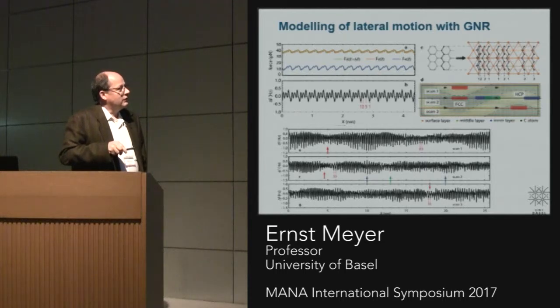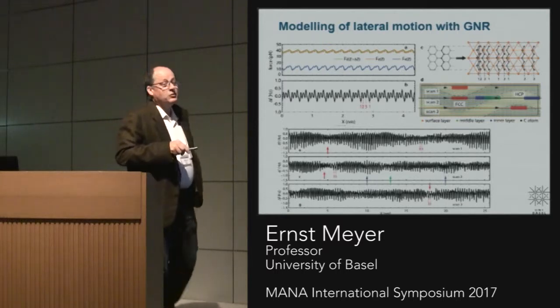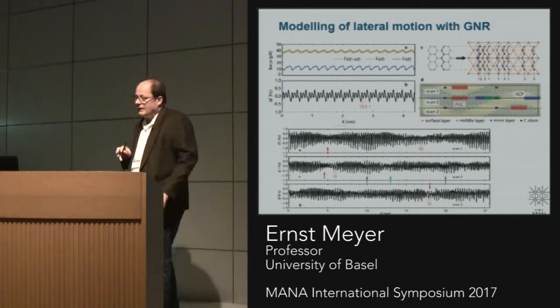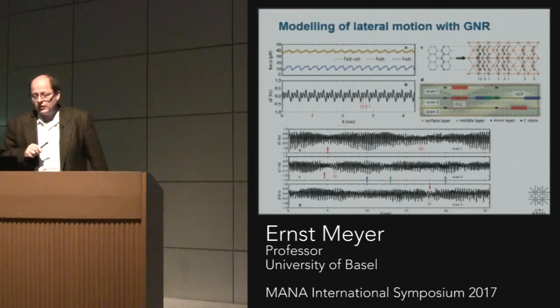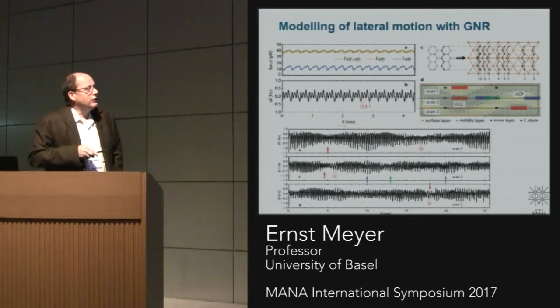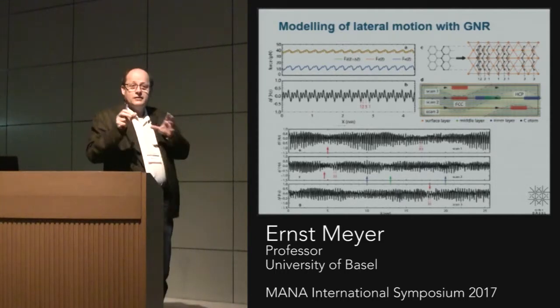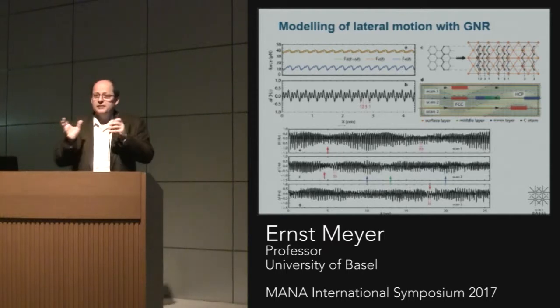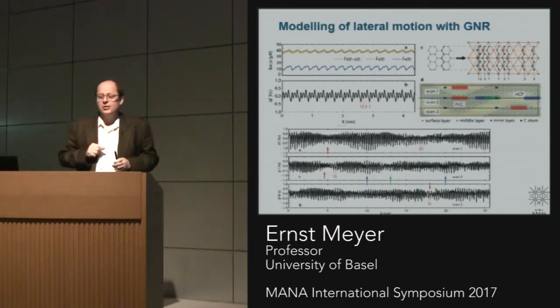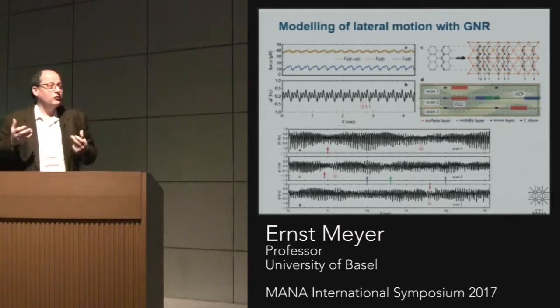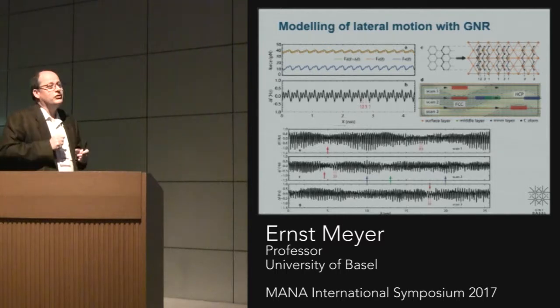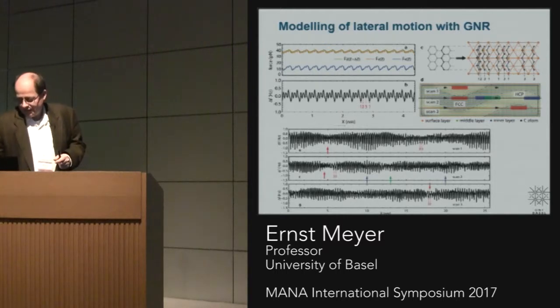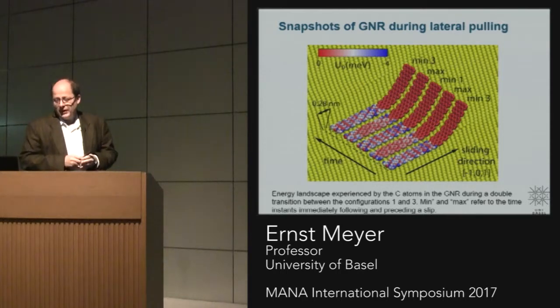But if you are in this transition regime between FCC and HCP, then we get the maxima. So it's somehow related to this commensurability of the contact. So you can really now start to exactly see how the misfit of the ribbon relative to the substrate is. So it's in a way a sort of surface science, but with something which is moving. So in that sense, of course, quite complex.